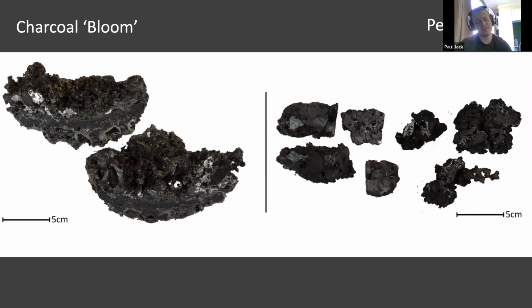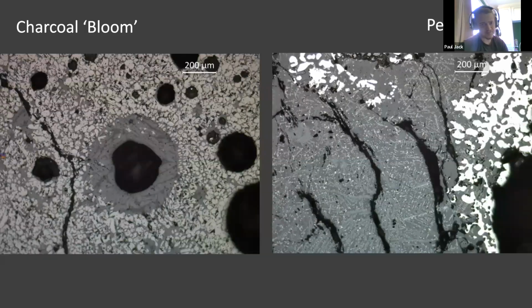But if we look to the right and have a look at the bloom that was produced by the peat fuel, we're maybe struggling to see the same sort of silvery areas. And when we do, it's quite foil-like. It's very thin and it's more strandy. But what that's telling us is that actually we might consider that smelt a bit of a failure. And so at this point, we might actually ask, well, we've got a bloom, but did the fuel actually work at all during the peat smelt? That's where the metallography comes in.